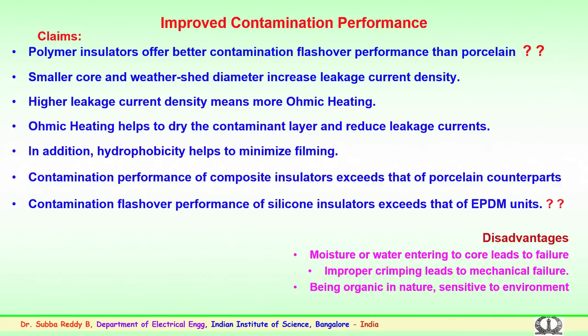In case there is damage to the insulating rubber on the surface of a polymeric insulator, moisture or water could enter the fiberglass core. This could lead to failure. There are reports of failures that have happened because of moisture entering and the formation of nitric acid, and this nitric acid causing brittle fracture of the fiberglass rod.